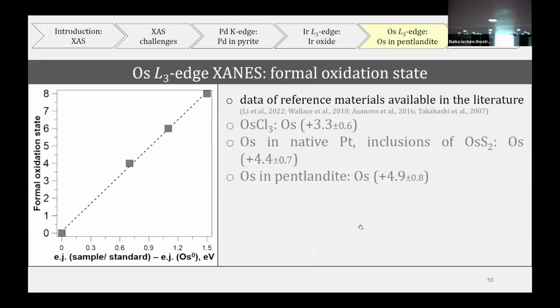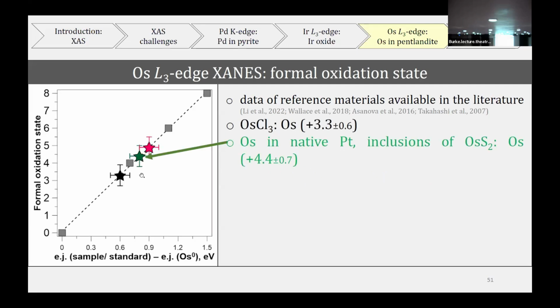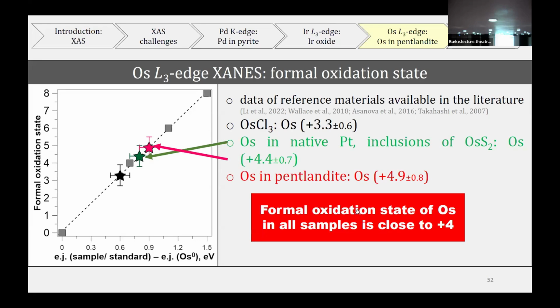We roughly estimated the formal oxidation state, using the same principle as I showed before with palladium. We collected reference materials data available in literature and estimated our standards, osmium chloride and osmium in inclusions of OsS2. Their oxidation states were slightly bigger than they're supposed to be, because it should be +3 and this should be +4 from the formal oxidation point of view. And osmium in pentlandite gave this strange number close to +5, but there is no osmium +5 in nature. Also, these calibration curves certainly give us slightly larger numbers than they should. So we suppose that the state is close to +4 in all the natural samples, in the green and red.